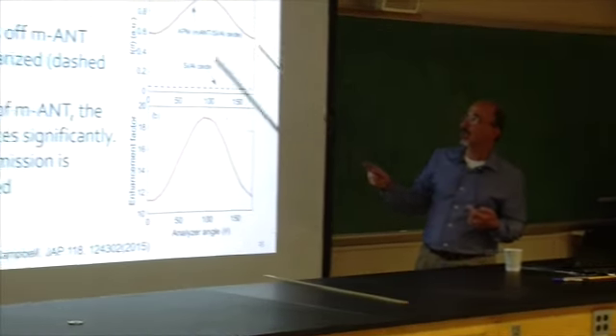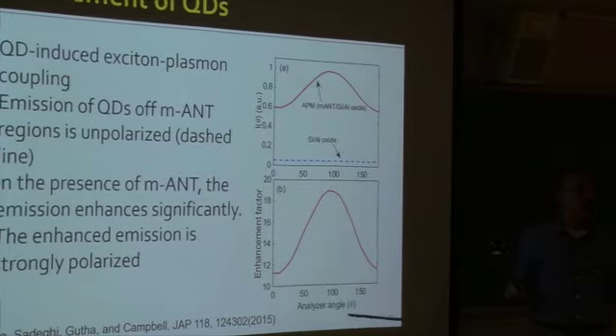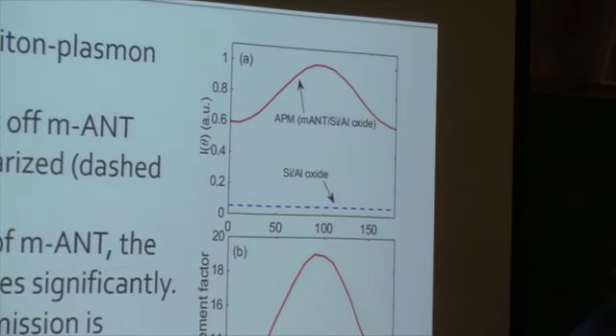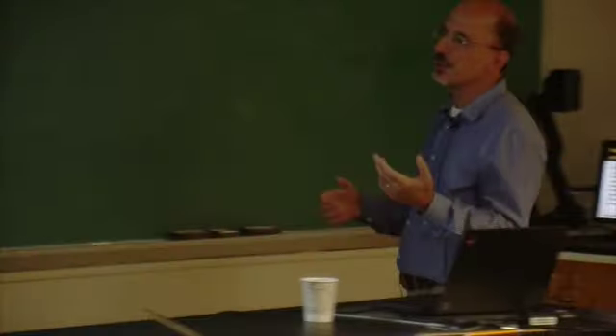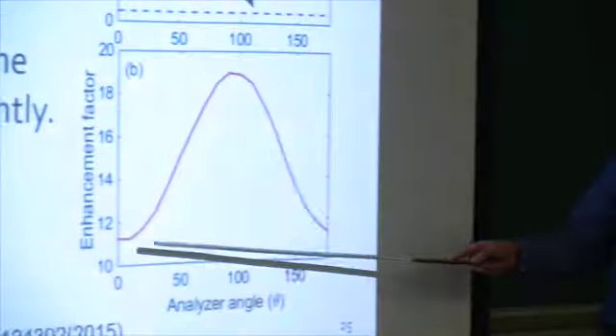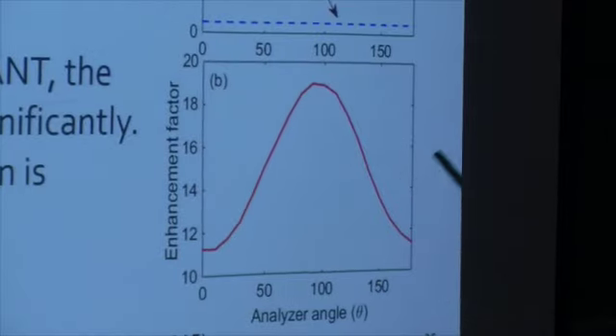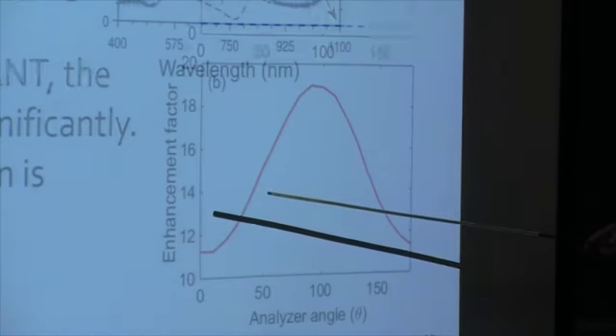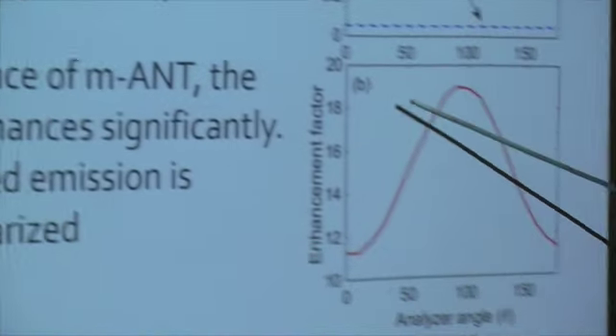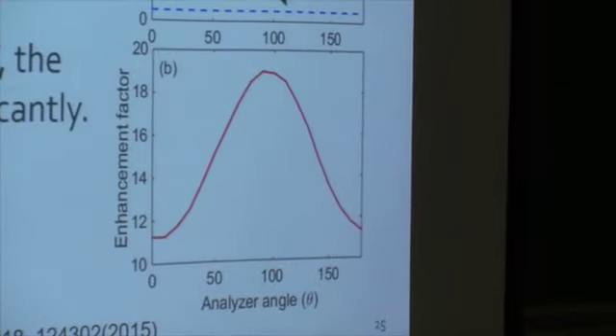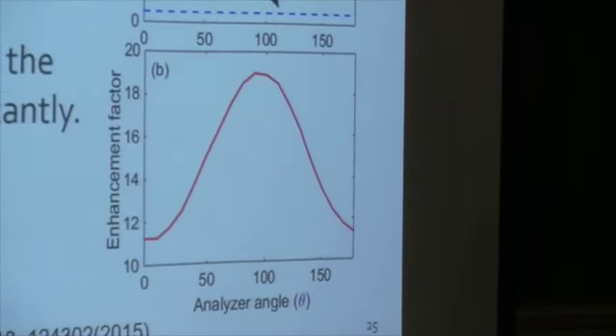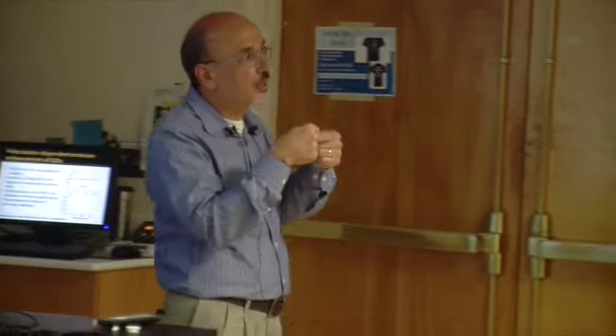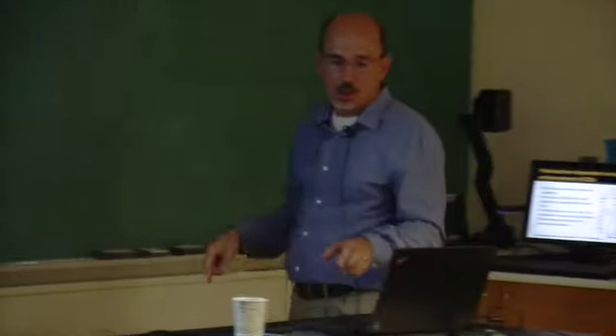Remember, this is normalized. So you can see that it is 0.6 to 1, 40% more light coming with the polarization along the short axis of the metallic nanoparticle. If you divide them by each other, it gives you a sense of how much enhancement you have. You have 11 times when the polarization is along the x-axis, but if you look at the polarization along the y-axis, it goes about 19 times. So the quantum dot emits with preferred polarization. And the reason behind that is that the quantum dot can actually excite that particular plasmon mode.